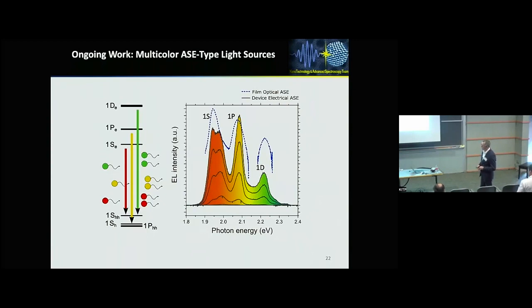Of course if you just think about optical device, the more monolayers the better to a certain extent. That's why this device works with optics but didn't work with electrical pumping because here you have transport across six monolayers. Resistivity, serial resistance is very high, you're heating up the device. We came to the threshold, we can measure temperature by analyzing the red shift of emission. We see it's 100K over what we want to be. Not only things happening in the quantum dots, turns out the silver—the absorbance in silver, optical absorbance in silver, turned out depends on temperature. Plus 100K dramatically increases optical absorption. Silver is also made by very cheap method, evaporation, it's granular silver. Temperature is critical, increases optical absorption. That's why we want to go to thinner, to reduce serial resistance on this end. The surface chemistry—you'd be surprised—oleic acid, that's it, original. When we started messing up with surfaces, as always with quantum dots you generate traps. Oleic acid, brute force, that's it. 2010. Victor, very nice talk. Maybe I want to connect it to building blocks to optimize the devices. My understanding is that you want to reduce the Auger recombination lifetime, which would suggest bigger particles because of the volume scaling. On the other hand, why don't you go to bigger particles? We want to stay in the quantum dot regime. We heard some talks very recently at the conference in Valencia from a Dutch group using big CdS particles which behave as bulk. Then you're not dealing with quantum dots. You can make them lase, then you can tune it—yes composition—but we prefer to serve the quantum dots. We see certain advantages like lowest threshold, still 30 amps per square centimeter. We still work with this small core, bigger shell, which helps us to reduce Auger, plus helps us to harvest charges. This is due to size quantization. We have now amplified spontaneous emission at four transitions, and there's a big need for ASE type light sources—not a laser, ASE type light, extremely bright, polarized. Display people would love that. Second question, the lattice is the assembly lattice—we don't care about order honestly. We only care about the density. If we have some spots uncovered, we have leaks, we have shorts. We just want a really dense coverage, that is important. It's spin coating, special regime of spin coating. Binary mixtures—that would be interesting. We have worked with those, but again, even with a single material, strongly confined material, you see emission color extends from red to green for transitions—1S, 1P, 1S light, heavy hole, light hole, P and S. Pretty much put the filter where you want and you get your color. Binary may be interesting but I don't believe we're going to work on that because I think that's enough with this very broad bandwidth. Let's thank Victor again and we'll move to our last speaker of the morning session.